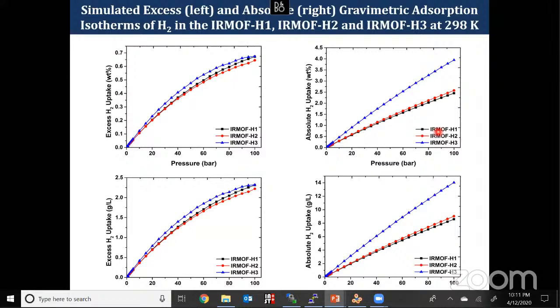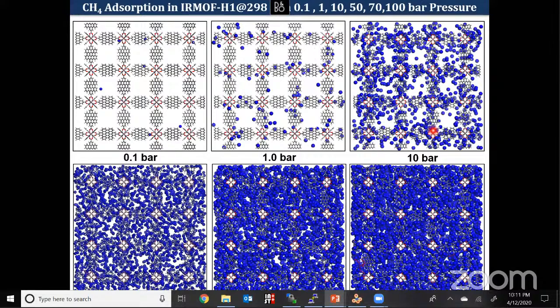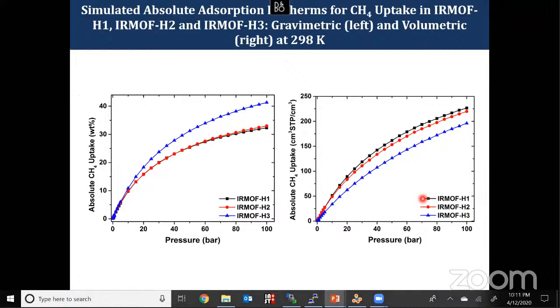And this is for methane. So here also the same scenario. The methane molecules initially populate over the connector atom, then they populate over the wall of the linker surface. Then the pore volume of the material is occupied with the gas molecules. So here also I did the simulation at 298, 300 Kelvin. So still it has not attained the saturation point. Still a lot of room is there to accommodate the gas molecules.